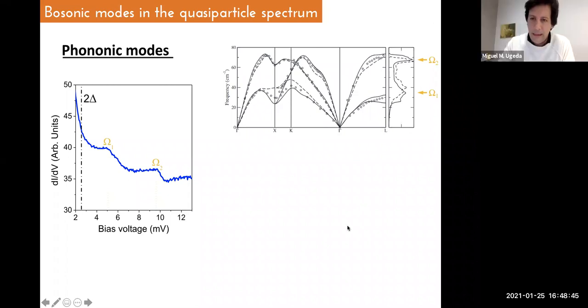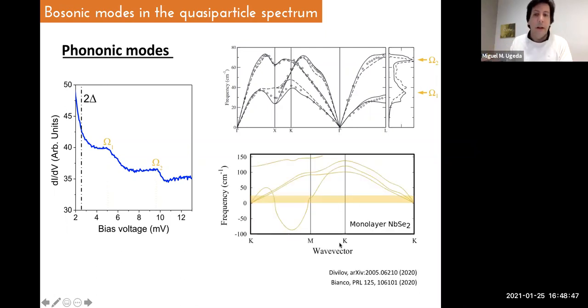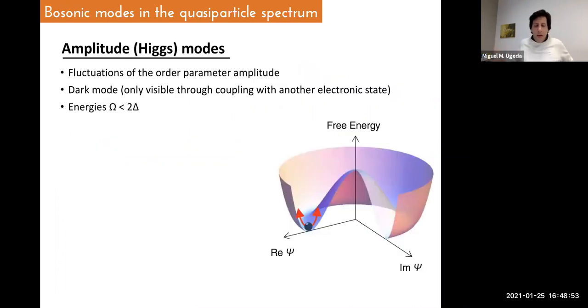Okay, so basically, I was saying that we can rule out the phononic modes because they are not there in the phonon dispersion. A more serious candidate would be the amplitude modes, also called Higgs modes, which are fluctuations of the order parameter amplitude.